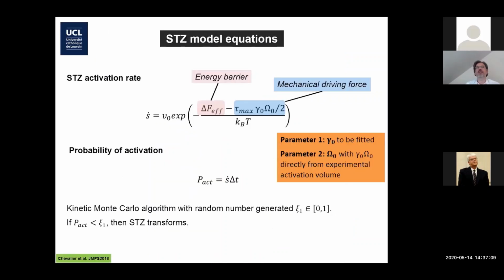A few words about the formalism. The rate of activation of a shear transformation zone is given by this expression, and for the derivation you can just follow transition state theory. The rate of activation depends on the energy barrier, which is reduced by the mechanical driving force you're bringing if you impose a shear, and this shear will work through the transformation strain over a volume, which is the activation volume, which I defined earlier. Now, there is a little bit of subtlety. What we found experimentally is not gamma zero. If you take the derivatives, etc., what you find experimentally is the strain multiplied by the true activation volume. But you got the idea.